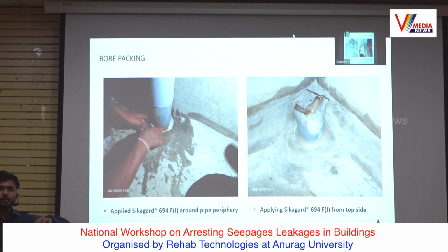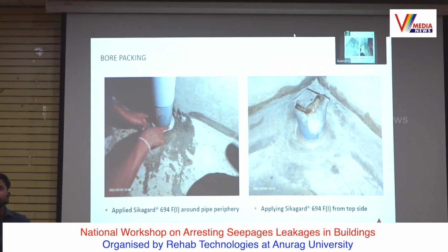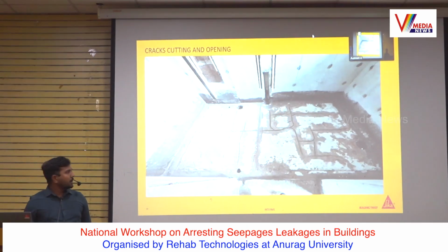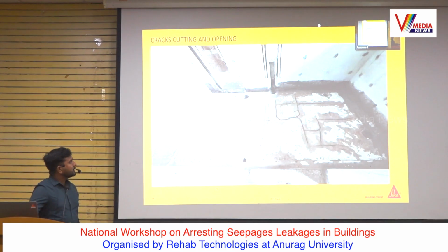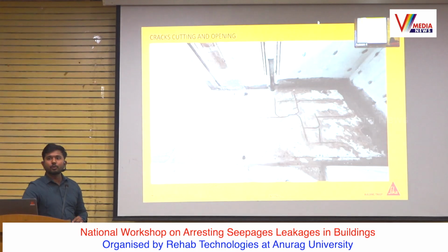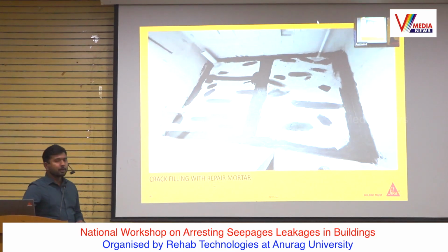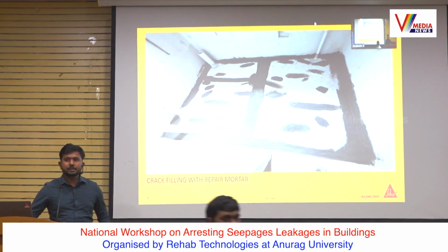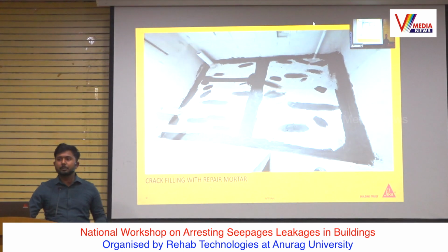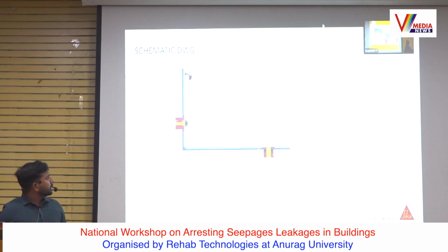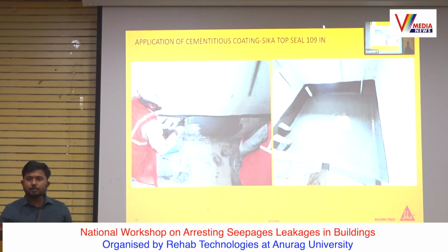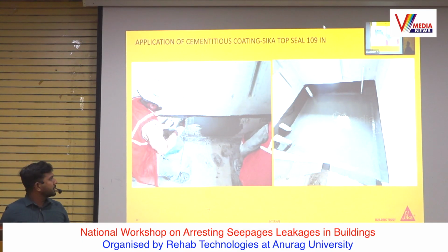This is moisture insensitive, even in dampness this will work. So this would avoid the cracks over the general purpose grout, and it would remove any leakages from the bore packings. After bore packing you need to go for crack treatment. Cracks should be cut in a V-groove fashion and then the repair mortar applied. We have our own repair mortar, Sika Monotop 122F, which is a pre-packed mortar. After that you need to apply the coatings, Sika Top Seal 109 or 107, any cementitious products you can apply.